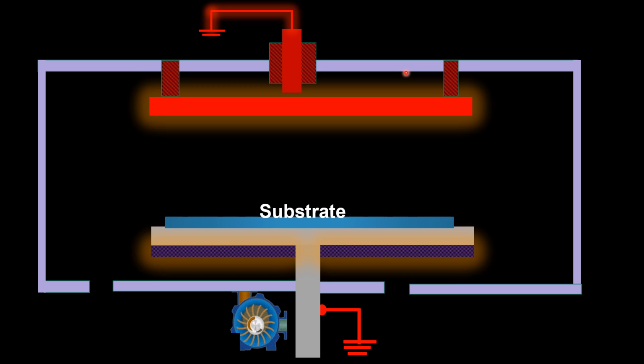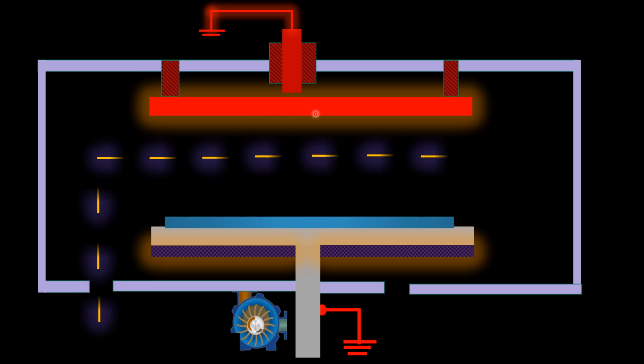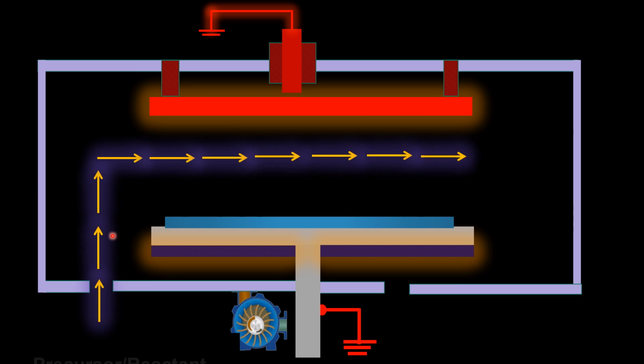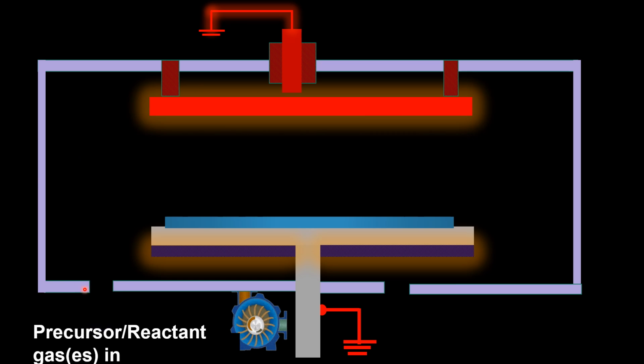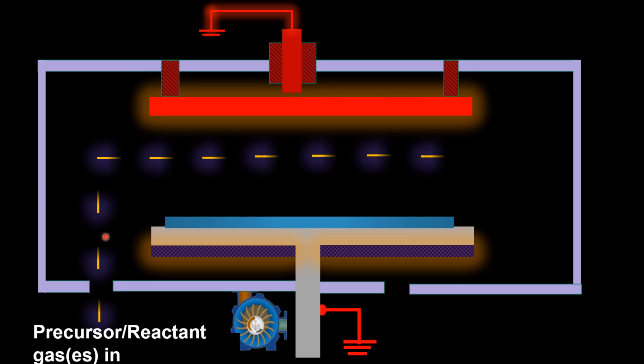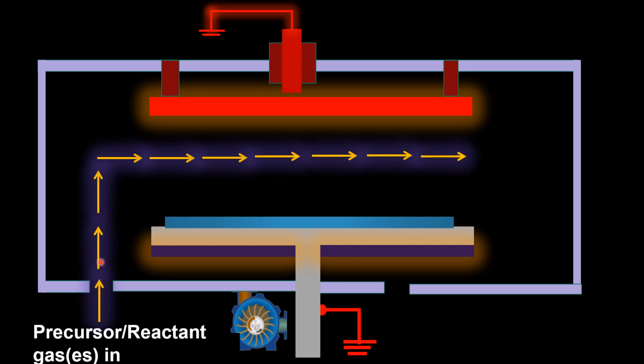After cleaning the environment of the PECVD reaction chamber, a high potential is applied with a radio frequency of around 13.56 megahertz inside the reaction chamber of the PECVD system. So your chamber is ready for deposition of thin films. So now you have to introduce a precursor gas inside the reaction chamber. The precursor gas will be introduced from a precursor gas line, which is present outside of the PECVD reaction chamber.